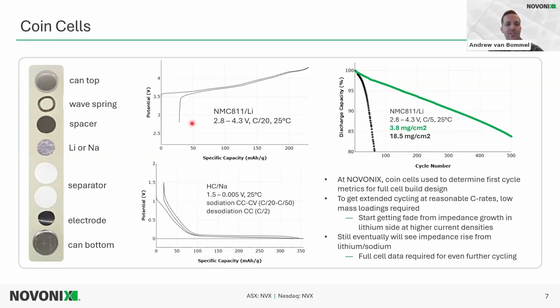So here's some examples of some cells that were tested using coin cells. So this is NMC 811 in a lithium coin cell, charging between 2.8 and 4.3 volts, and discharging back to 2.8 volts. The C rate is C/20 in both charge and discharge direction. We generally don't put CV steps on that first charge and discharge, and this one was done at 25 degrees. And this is generally what we see for any NMC 811, which is usually around 83% nickel in that transition metal layer.